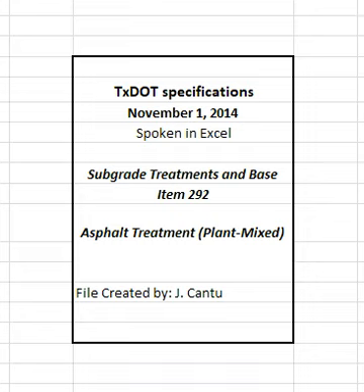the contractor's expense. Roll at a speed producing at least 10 blows per foot unless otherwise directed. Keep the drums moist with water without using excess water, and do not drop diesel, gasoline, oil, grease, or other foreign matter on the pavement. Where specific air void requirements are waived, furnish and operate compaction equipment as approved.